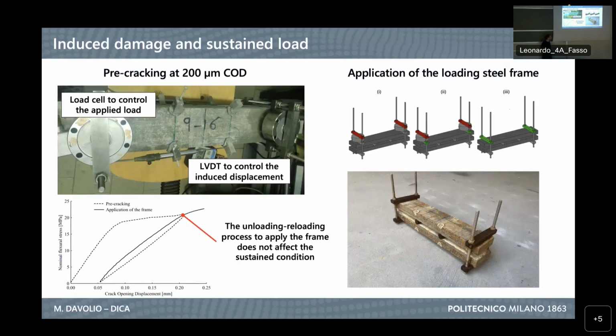Here, I present the induced damage, which, as I mentioned, was pre-cracking, and we targeted these 200 microns crack opening displacement. The idea was to obtain a crack width which would be observed from the microscope. We did some trials before finding an accurate crack opening, because literature has some scattering of approaches from 50 to 300 or even more microns. And we pre-cracked the specimen with a 4-point bending scheme, because the idea was then to reproduce the loading condition, which with this steel frame, you can see in this picture, that aimed at keeping the load, 4-point bending loading, constant over time during the exposure.